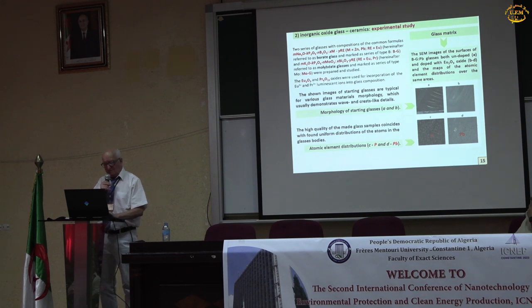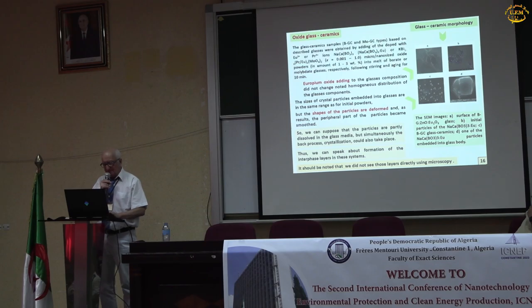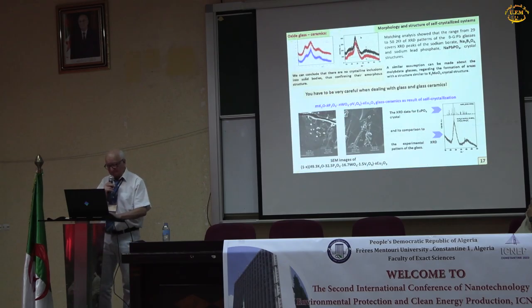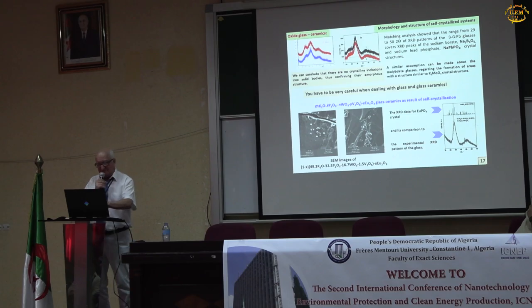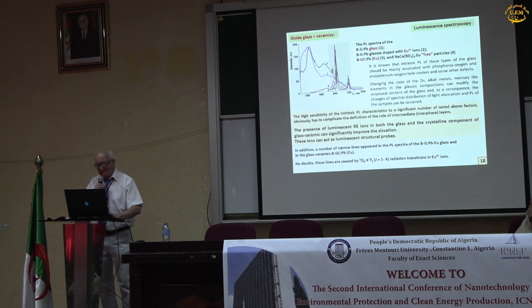So you see some experimental data about morphology of this glass ceramics, various types of glass ceramics, distribution of atoms on the glass, and you see the image of the composite materials, glass with embedded oxide particles, and some data about XRD of glass, powders and glass ceramics. And I'd like to emphasize the possibility of use the luminescence method.